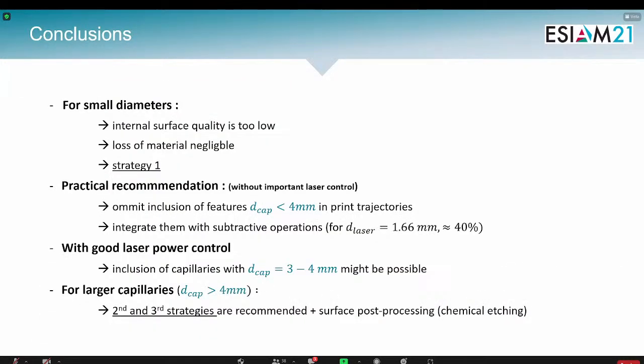And finally, to conclude, for small diameters, strategy 1 is recommended. And then as a practical recommendation, we would omit the inclusion of the features down to 4 millimeters. And if you have a good laser power control, it can go down to 3 to 4 millimeters. It might be possible with a good laser control. And then for larger capillaries, the second and the third strategy are recommended. That was it for my presentation.